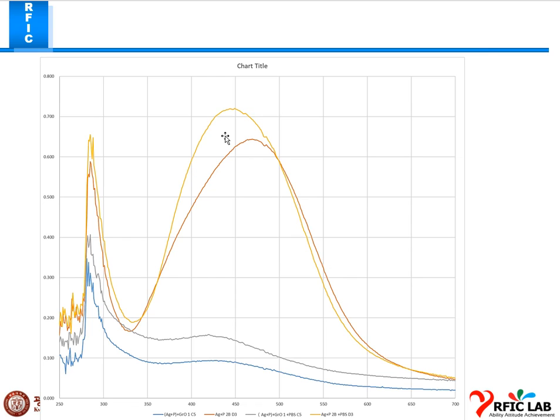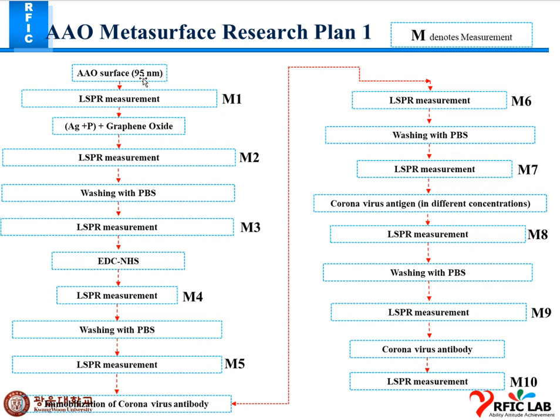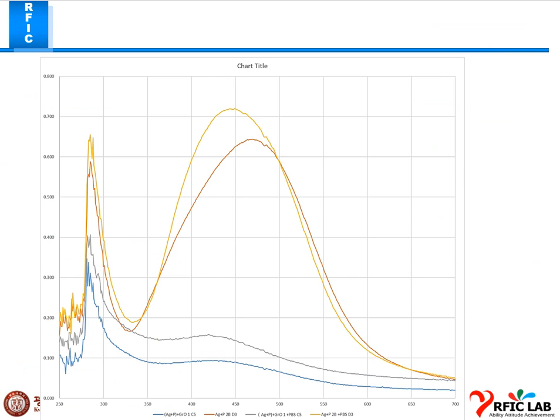But if we check our AAO, the pore size is maximum 95 nanometer, that I already explained in my research plan. So the graphene flakes do not penetrate into the pore surface, and also act like a barrier to the Ag particle entering. So we thought that we have to buy the MUA. It acts like the graphene oxide, with the same free carboxylic groups as the graphene oxide, but the flake size, the particle size, is very small compared to the graphene oxide flake size.